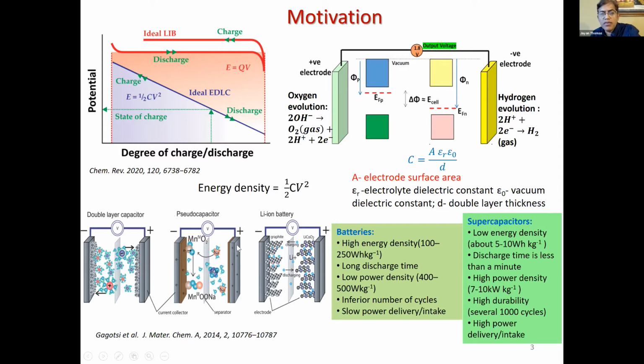Here you can see a comparison of the different devices, but I am not going into details. But the major difference is, for the lithium-ion battery, you have a bulk electrode where the lithium ions diffuse into that one, and it takes time for that diffusion to take place when you have a bulk electrode. And that's the reason why it takes time to charge, and also it takes time to discharge those ions. Whereas in the supercapacitors, you can enhance the surface area. The energy storage takes place at the surface or very close to the surface, but this can intercalate or de-intercalate the ions very quickly. So that's the reason why it can give the huge power.